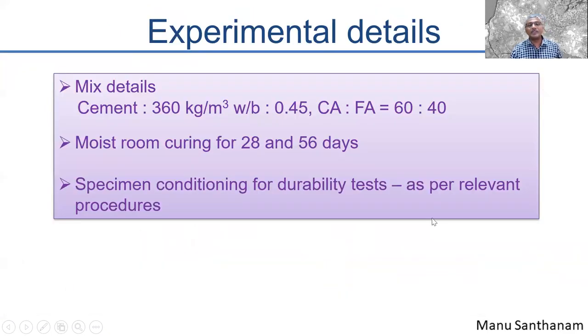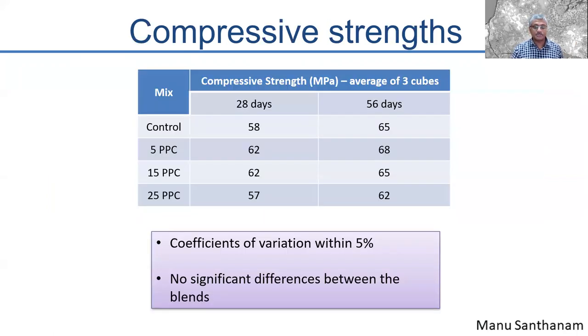So we went with a common mix design for all the different types of cementitious blends. The cement content was 360, water binder ratio is 0.45, and coarse to fine aggregate ratio is 60 to 40. We did conventional moist curing for 28 days and 56 days. And conditioning was done for the durability tests as per the regular procedures.